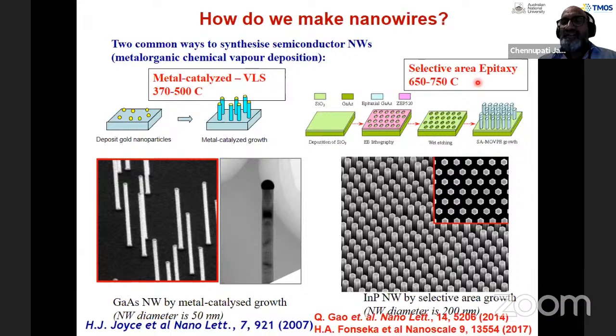So the alternative technique is called selective epitaxy. In this case, we don't use any metal nanoparticles. We deposit some silicon dioxide by the PECVD process, plasma enhanced chemical vapor deposition, and then put some photoresist or ZEP resist, an electron beam resist, and then do electron beam lithography and transfer those patterns through the silicon dioxide by wet etching so that you can expose indium phosphide in this case, and the other parts are covered by silicon dioxide. Then you put this into the MOCVD reactor, heat it to somewhere between 650 to 750 degrees Celsius, and then introduce the gases needed for the growth of indium phosphide, trimethyl indium and phosphine. These gases dissociate, and then nanowires beautifully grow here.